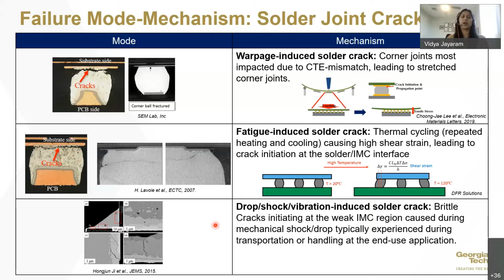And thirdly, you can have solder joint cracking also because of mechanically induced defects. If you have manual handling or storage where your package gets dropped or experiences some type of shock or vibration, that leads to more brittle cracks compared to the warpage or the fatigue-induced cracks. You would see more brittle cracks, and that would indicate that it's some sort of mechanical stress-induced damage.